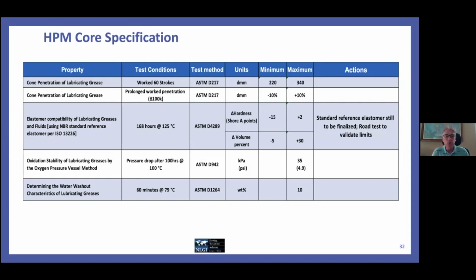The next one's elastomer compatibility of lubricating greases. Gareth mentioned this as being the initiator of why the GCLB specification was being re-examined because of issues with that test and with the elastomers in that test. So where we are today on this is we have specified NBR standard elastomer per ISO 13226. This is different NBR elastomer than is used in the GCLB. And while I mentioned there in the actions that the reference elastomer is still to be finalized, the elastomer task force that worked this issue specifically has pretty much landed on the ISO 13226 specification, but now we're working on making sure we've got adequate sources of supply for this elastomer.